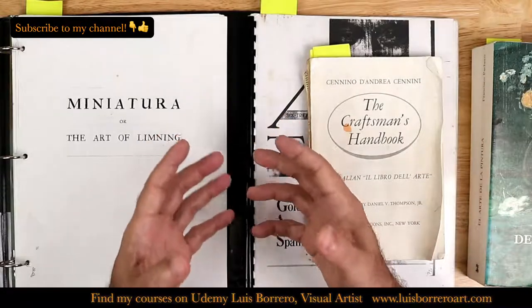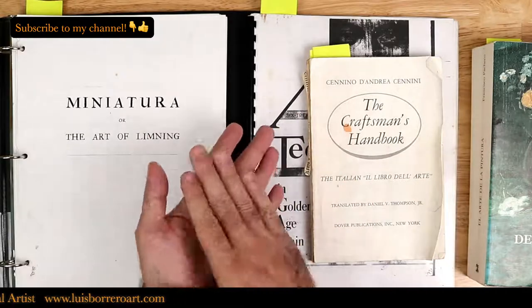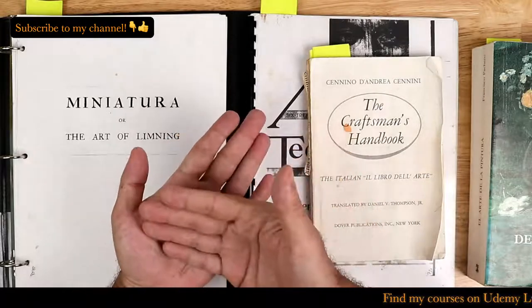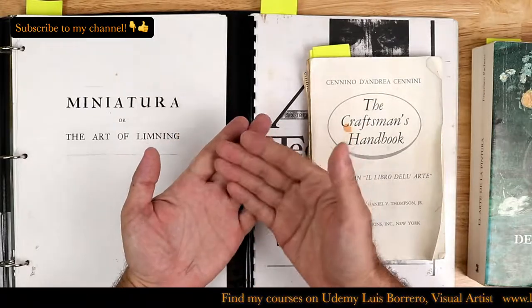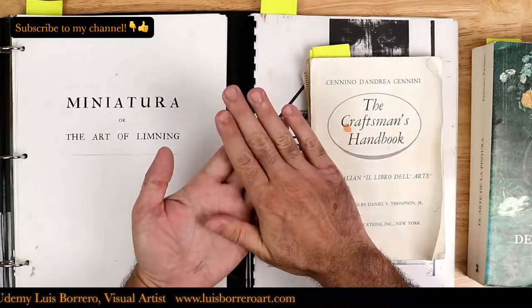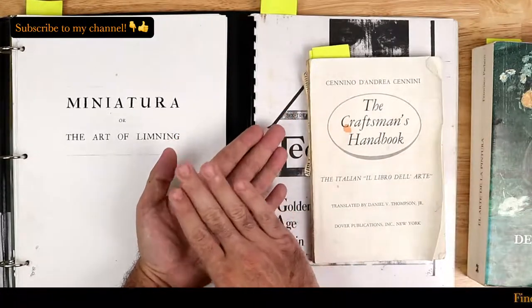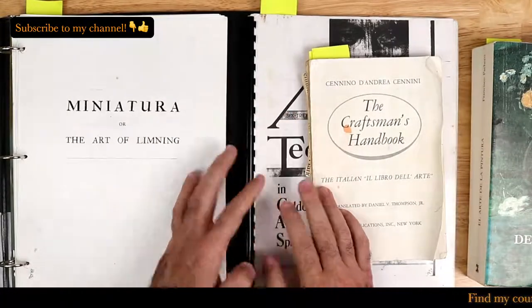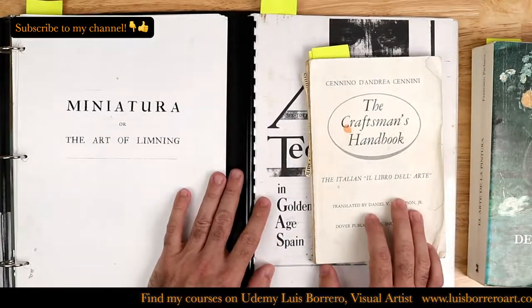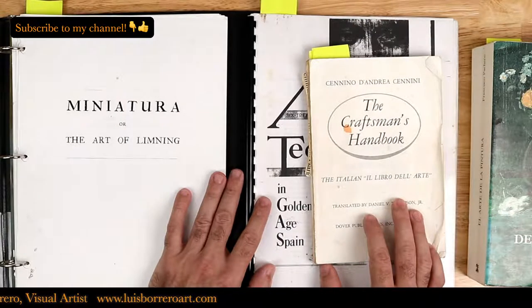And what is exactly lead white? Well, if you take a lead metal and you expose that metal to an acidic vapor, the corrosion on that metal will be white. And there are two processes. First, it turns into lead acetate, and then it will later transform into basic lead carbonate. I'm going to be detailing that process. So I've gathered some photos of the process for you here.